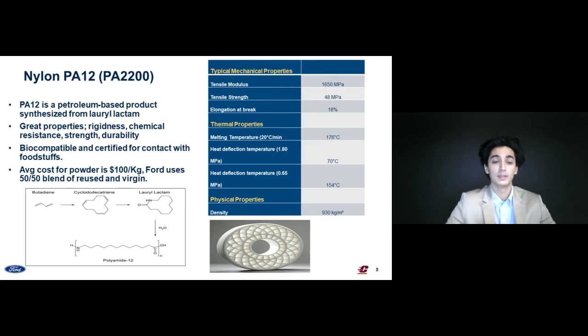This reused powder can sometimes be thermally damaged as the 3D printing process goes to really high temperatures. So some of it can be thermally damaged, and really what we're trying to do with our project is to make sure that we have some sort of quality control procedure to make sure that the powder, the 50-50 blend, is of optimal quality.